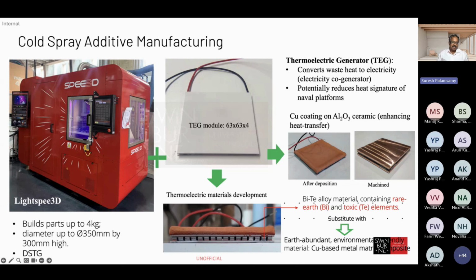So this machine can print up to roughly 4 kilograms. The diameter can be 350 by 300 millimeter height. In this particular case, this is an example which we worked on with a defense partner. The main application is aluminum oxide tiles. Ceramic tiles are shown here for thermoelectric material deposition or development.